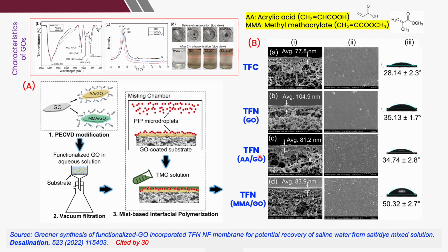But if the graphene oxide is modified by monomer, either AA or MMA, you will see that the layer becomes thinner. This is because once you modify the graphene oxide, the exfoliation actually is better. Then this reduces the stacking effect of the graphene oxide.